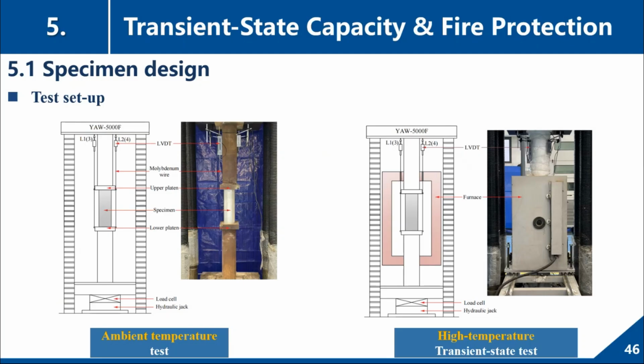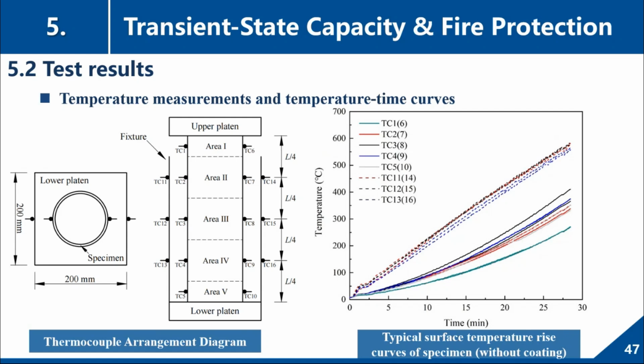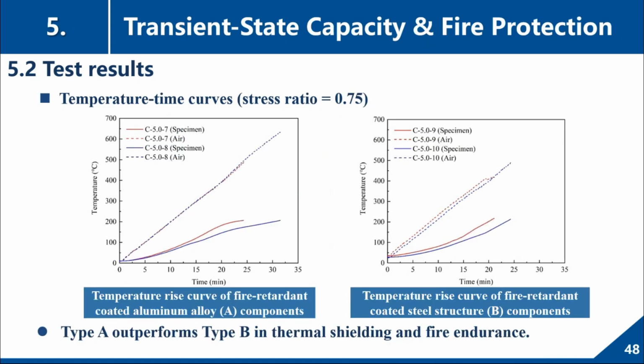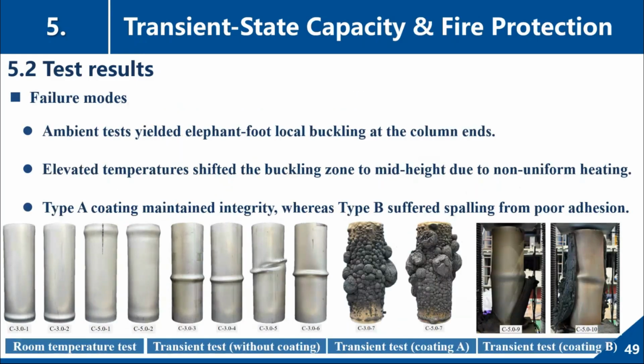These are the test setup, and these are the temperature measurements and the temperature-time curves. First, we found from the temperature-time curves of the two coating-protected members that type A outperforms type B in thermal shielding and fire endurance. And from the failure modes, it's more evident. First, let's see the ambient temperature test. It shows elephant foot local buckling at the column ends. I think this is very common. But for the elevated temperature test, it's rather different, because in our furnace the temperature in the middle is higher than at both ends. So the buckling point shifts to the middle.